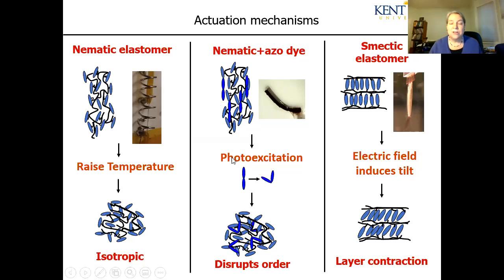In the case of the light actuation, that polymer is doped with an azo dye, some kind of azobenzene derivative that undergoes photoisomerization, or photoexcitation. So when you have the material in the relaxed state, the trans state, when it absorbs a photon of just the right wavelength, it will undergo a conformational change to a cis or bent state, which disrupts nematic order. And then the material that's been exposed to light will also locally shrink. In this case, the top of the little cantilever, the part of the sample that was impacted by the light, has locally shrunk, and the back didn't get the light, so it bent because the front shrank and the back didn't. In this case, the direction of nematic order is parallel to the long axis of the beam, so it bent up, kind of like the bimetallic strip that we all study that is used as a thermometer, which bends from a change of temperature.